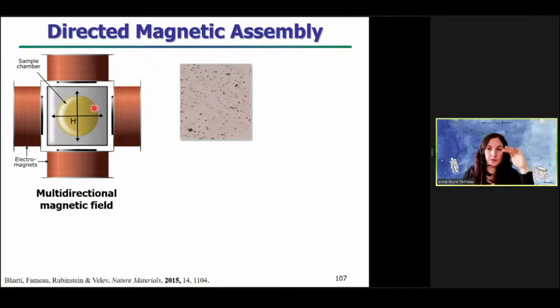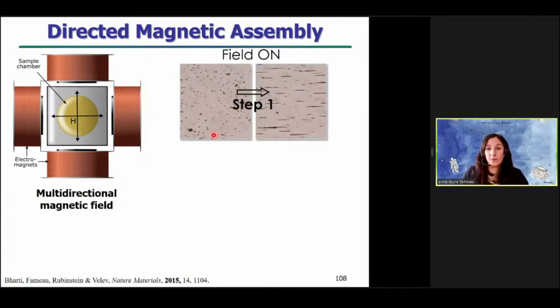We put the dispersion inside the sample chamber, and we just follow the particle assembly by optical microscopy. Here you can see a picture of the nanoparticles and the microaggregates inside the fatty acid soap self-assembly dispersion. We just turn on the magnetic field in this direction, and you can see that the magnetic field just pulls all together the nanoparticles and microaggregates along the direction of the applied magnetic field, and they form some filament structure.